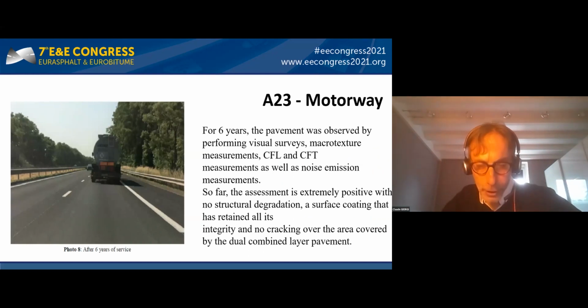For 6 years, the pavement was observed by performing visual surveys, macrotexture measurement, CFL and CFT measurement, as well as noise emissions. So far, assessment is extremely positive, with no structural degradation, and the surface coating that has retained all its integrity.